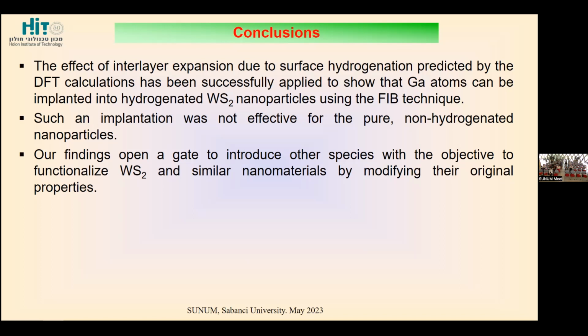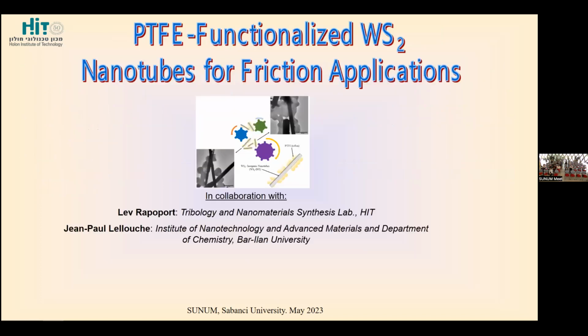Okay. If we are talking about the functionalization of nanoparticles, we did a quite different study. This was used for mechanical properties: the Teflon coatings of WS2 nanotubes. Nanoparticles of WS2, fullerene-like nanoparticles, are already used for lubrication because they are ball-like nanoparticles, so they can indeed decrease friction. But what about the nanotubes? Generally, nanotubes are not so beneficial for friction reduction because they are easily broken. But then some of us proposed to coat them with Teflon.